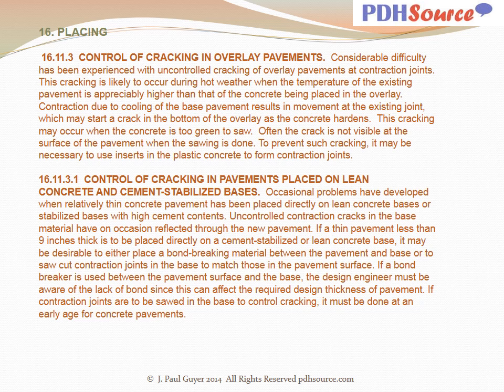Considerable difficulty has been experienced with uncontrolled cracking of overlay pavements at contraction joints. This cracking is likely to occur during hot weather when the temperature of the existing pavement is appreciably higher than that of the concrete being placed in the overlay. Contraction due to cooling of the base pavement results in movement at the existing joint, which may start a crack in the bottom of the overlay as the concrete hardens.